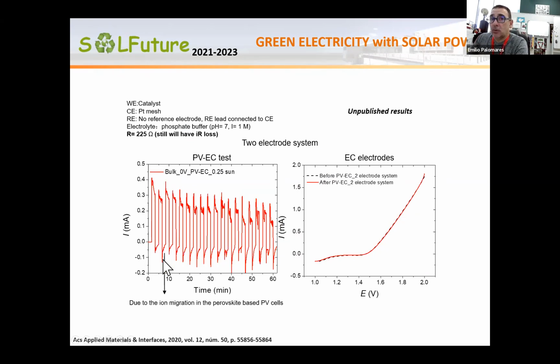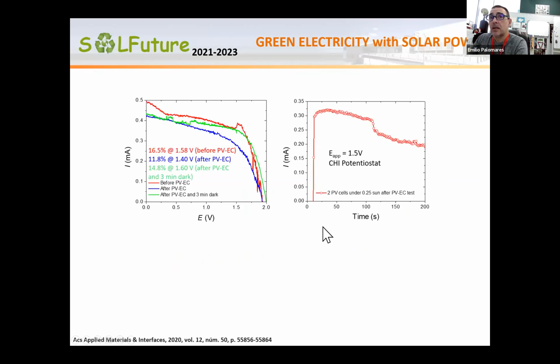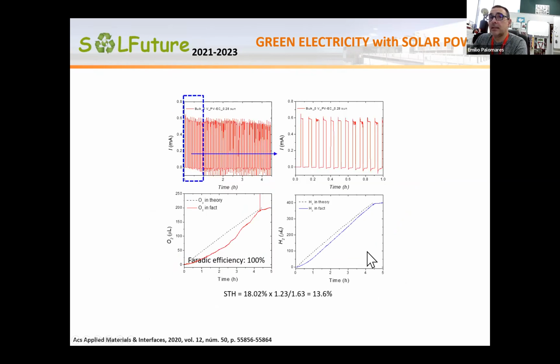When you use chopped light, then you don't have this issue, and you can still use this solar cell as, let's say, a power source for the catalysis. This is before and after the formation of hydrogen from water. These are the IV curves before and after the use as a power source for the catalysis. And this is how the current changes over 200 seconds, which is what we use to do the catalysis. So here is what I was telling you about the chopped light. Here is a zoom on this area.